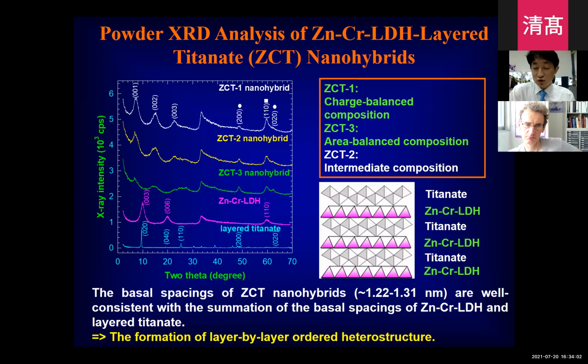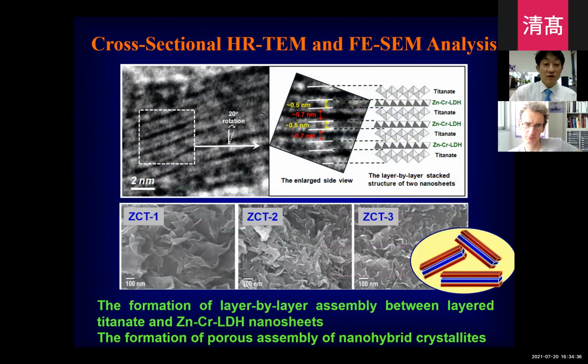It has newly defined c lattice parameters, so we can confirm the formation of the artificial superlattice from the XRD analysis. As you can see here, we observed the distinct low angle shift of the 00L reflection. So this is the evidence for the formation of the layer by layer ordered superstructures. The calculated lattice parameter is well matched with the summation of the thickness of each LDH layer and the titanate layers. We further confirm the formation of the superlattice structure from the cross-sectional TEM analysis.